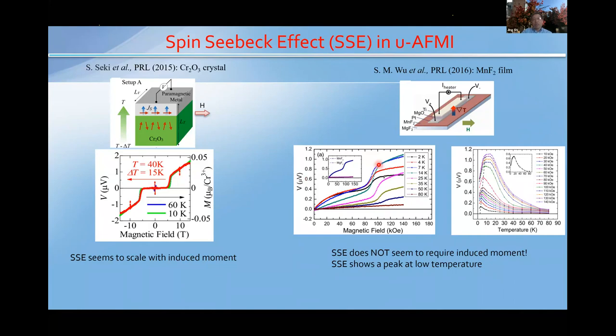On the right-hand side, in this manganese fluoride case, the samples are epitaxially grown films. You see clearly there's a spin flop transition, and the signal is finite even below the spin flop transition. So there are some differences between these two uniaxial antiferromagnets. What is more interesting is the temperature dependence: there is a peak at some temperature below the Néel transition temperature.